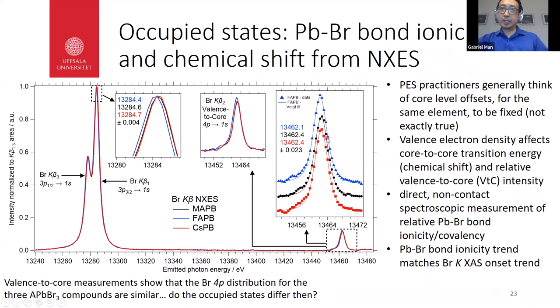Here I fitted the bromine 4p distributions, which are asymmetric, we know that from our ground state density of states, but their purpose was just to extract the peak maxima value over here, and also to see how well it fits on the higher energy side. So something interesting is that despite the structural differences, the bromine 4p distributions are rather similar for the three different compounds. That raises the question of what's actually different in the occupied states.